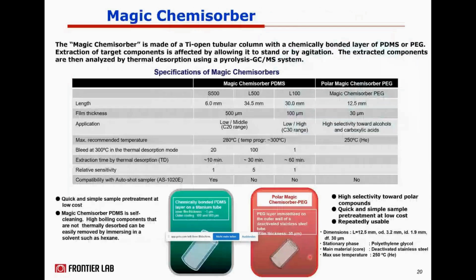Magic Chemisorber, what is that? Magic Chemisorbers are stir bar sorptive extraction elements, and they have a titanium open tubular design with an inert treatment, like also done in the Ultra ALLOY capillary columns. They have a chemically bonded layer of PDMS or PEG on the outer wall. So PDMS, as you know, has a high affinity to non-polar compounds, while PEG has high selectivity to polar compounds like alcohols and carboxylic acids.